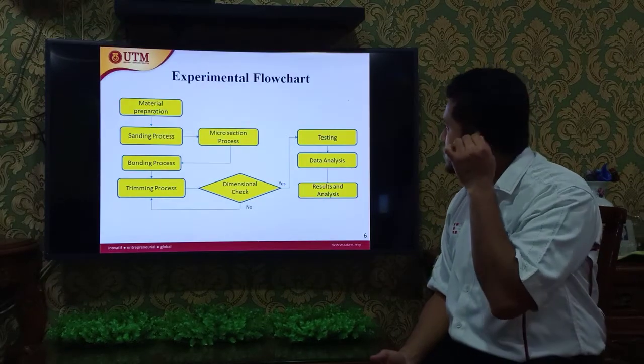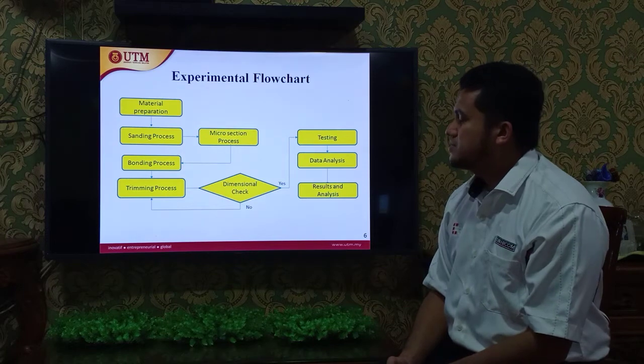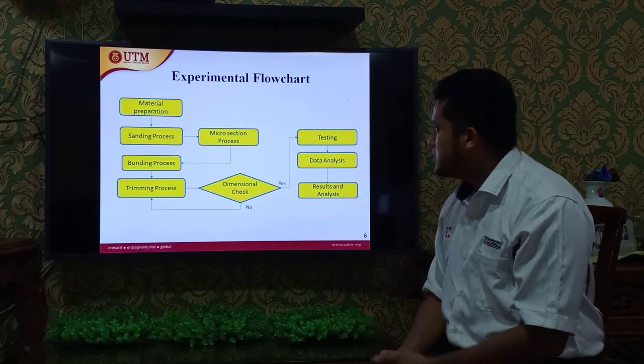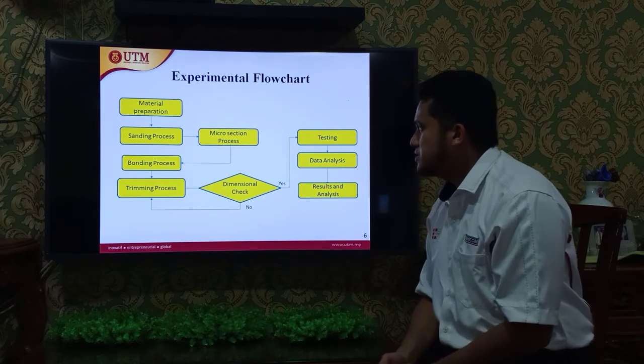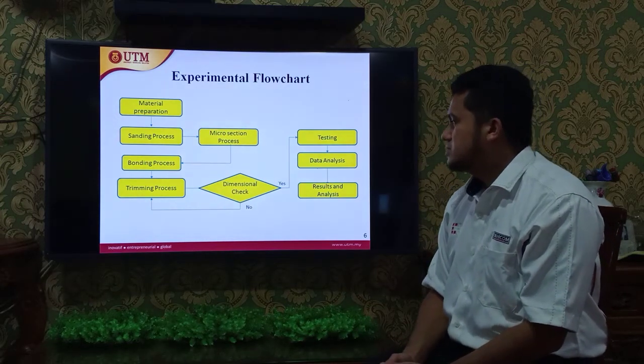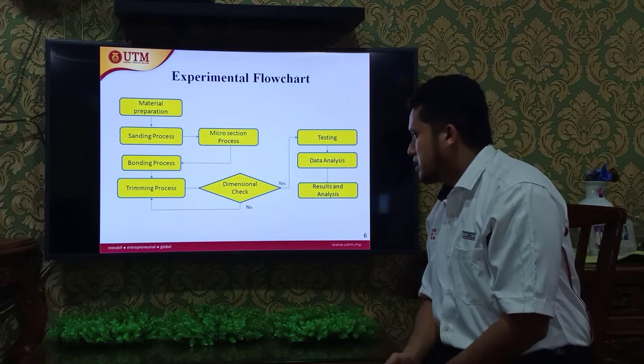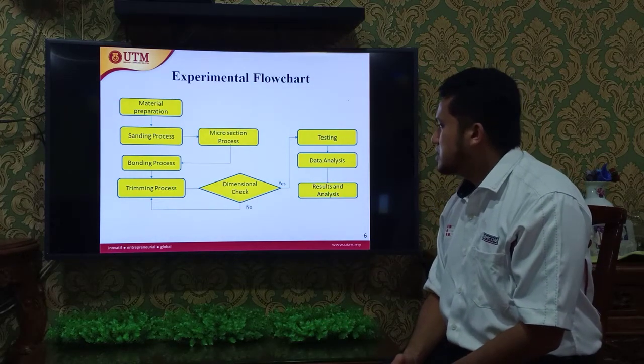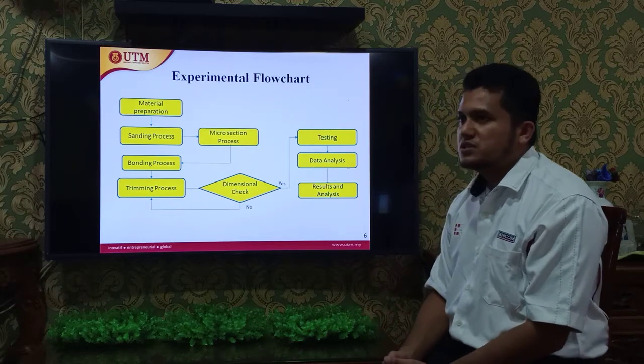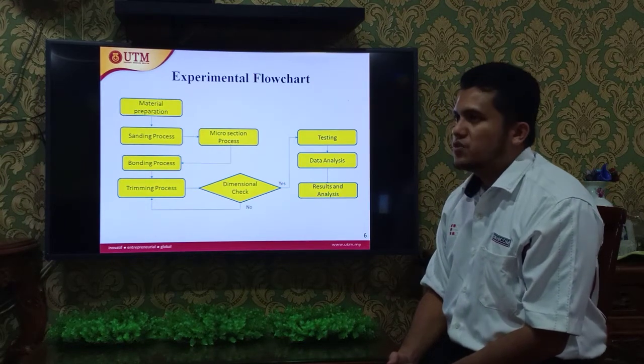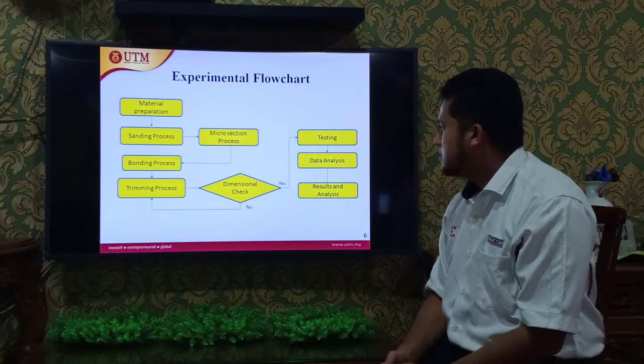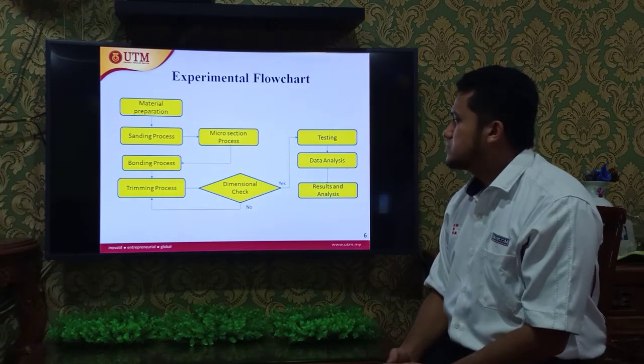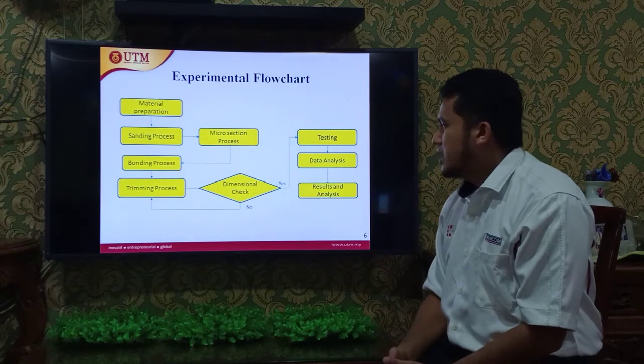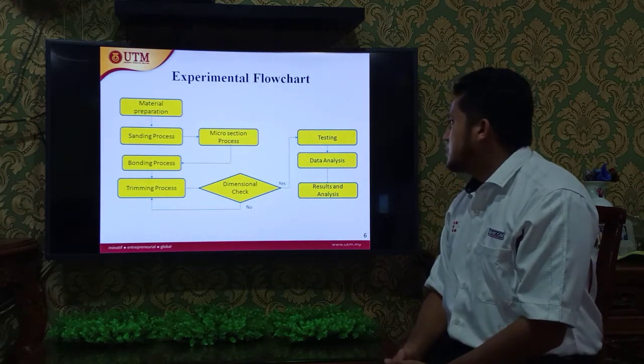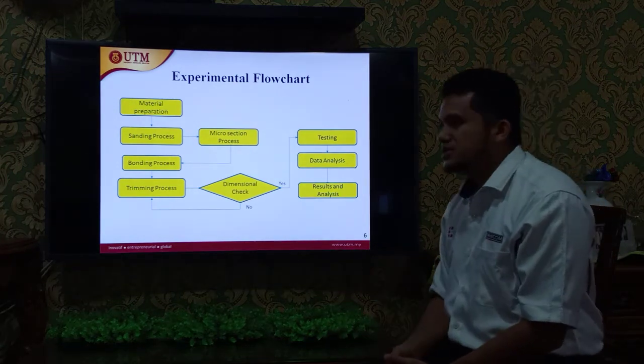This is the experimental flowchart. First, material preparations. Second, the sanding process activity, microsection process, bonding process, and trimming process. For the dimensional check, if yes, the dimension is as per requirement, we proceed to testing. If no, we revert to the trimming process until the dimension meets the requirement. After the testing, we get the data analysis and we conclude the result and analysis.